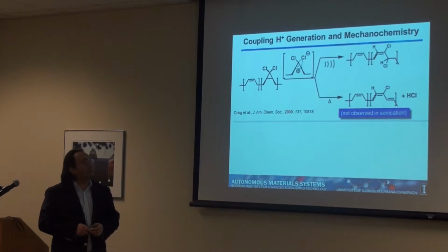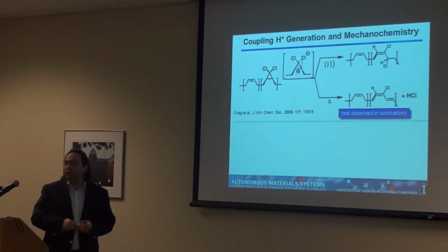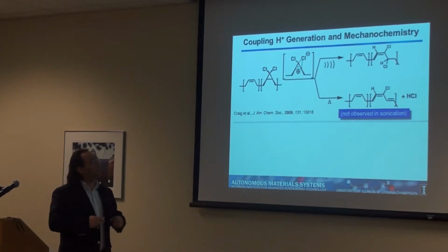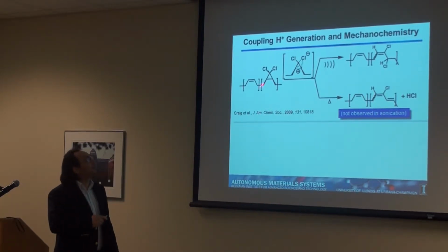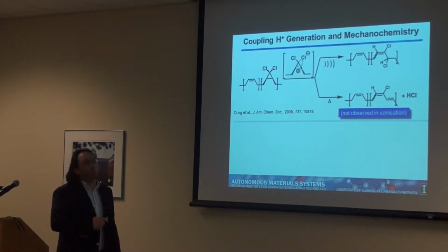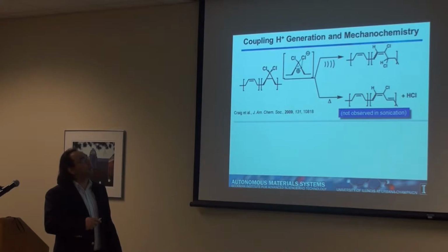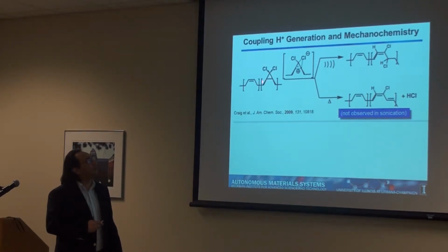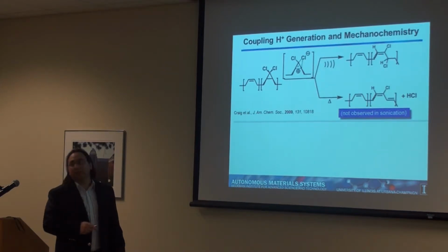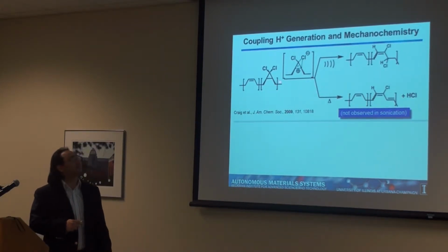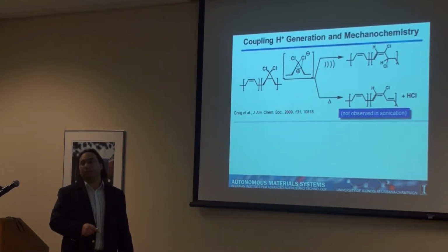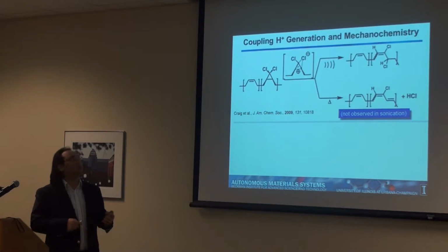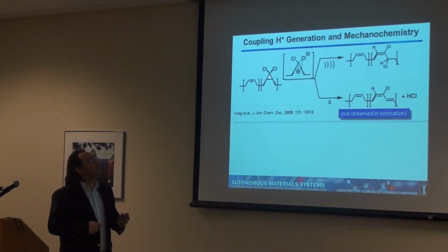My work basically started by looking at other people's work. In this work by Craig from Duke University, he showed that this chemical group, called dichlorocyclopropane, undergoes a chemical reaction when you apply mechanical force to it. You open the cyclopropane, make a new double bond, and the chloride jumps to the carbon beside it. The interesting thing is that when he took the same polymer and heated it, he produced a lot of acid. So we looked at this and asked how we can change this in order to go to this pathway and not this pathway.